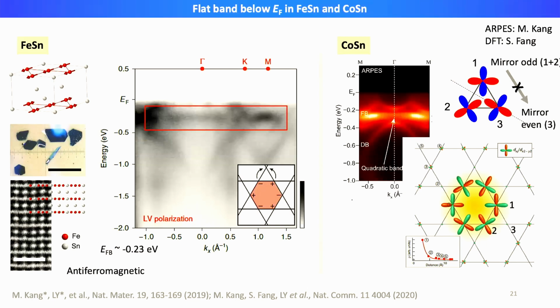Right. And here we can still see that a very similar mechanism of destructive interference is at play. If we look at the hopping of states 1 and 2 to the third site, for instance, the hopping from 1 and 2 as a combination to 3 would be strictly forbidden. In the d orbital case, this comes from 1 and 2 having a different eigenvalue than 3 under the mirror symmetry, where the mirror plane is drawn here. So this is still a very good real space eigenwave function of the flat band.